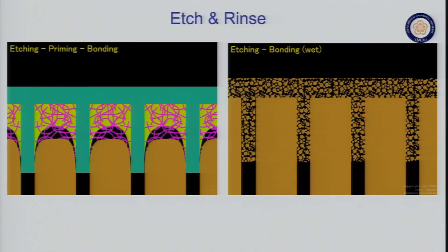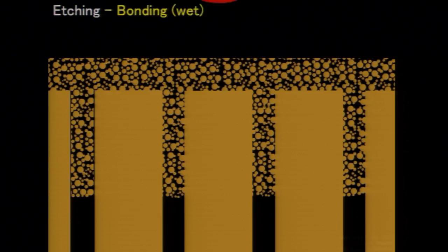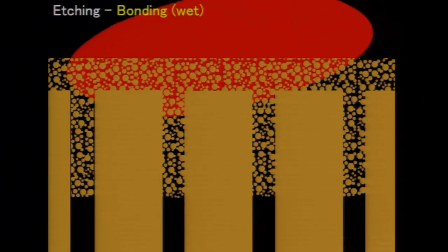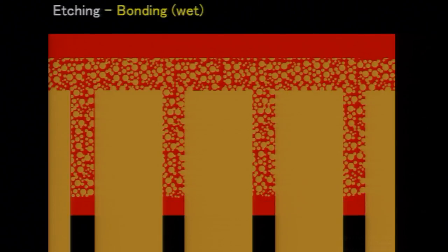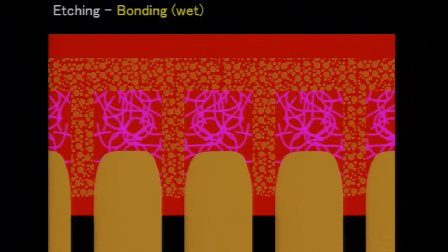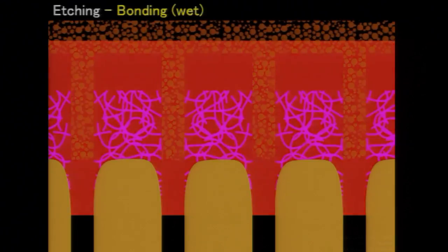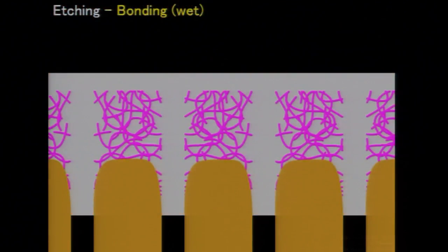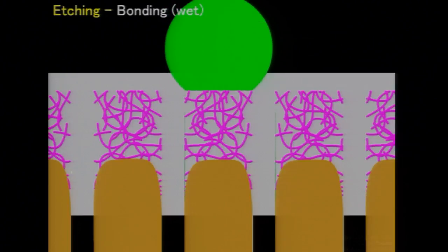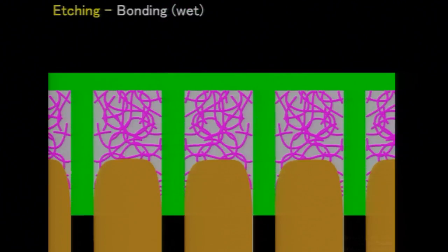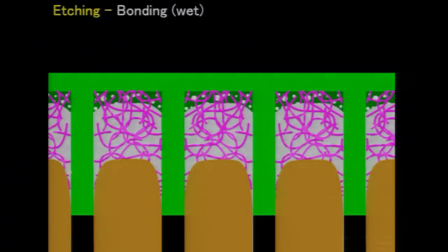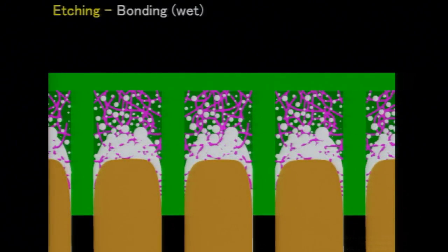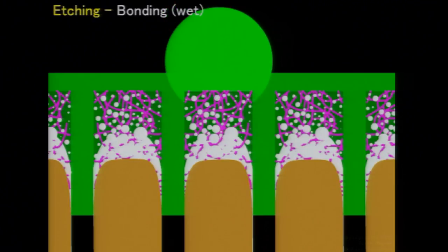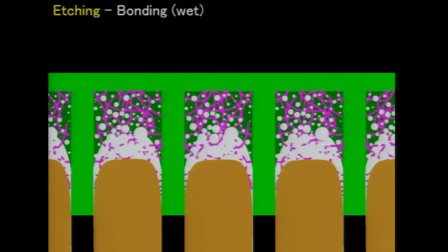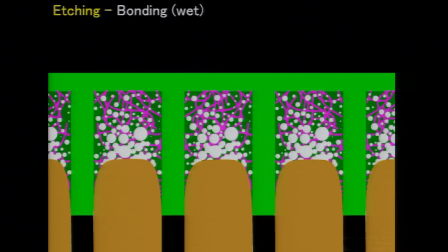In the case of the wet bonding technique, this is a nice idea to prevent the shrinkage of the collagen layers. We are recommended to maintain some amount of water to prevent the shrinkage. We should not dry the surface. The space among the fibers is maintained, and we apply the bonding resin. To remove the amount of water at the interface, we are required to apply it 2 or 3 times. Then the amount of water will decrease. Then we polymerize it.